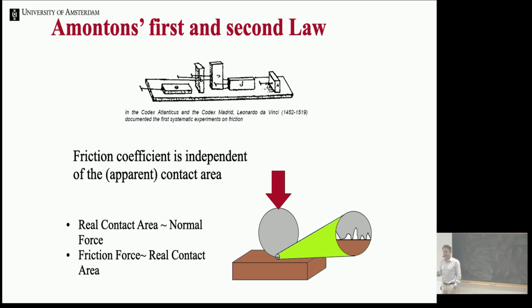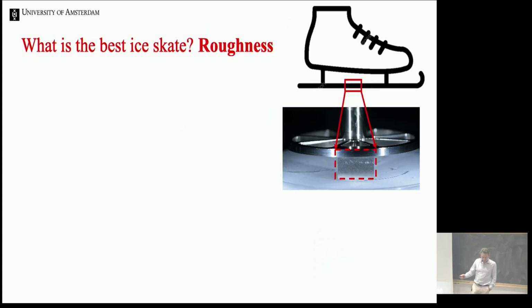The friction coefficient of wood on wood is 0.4. It's actually not 0.25, but that's another story. The friction coefficient of steel on steel is 0.3. And that's very useful for engineering, and it all boils down to believing Amontons' law. And so for a physicist, this is perhaps not completely obvious, because the physics is actually very complicated, but for engineers this actually works.